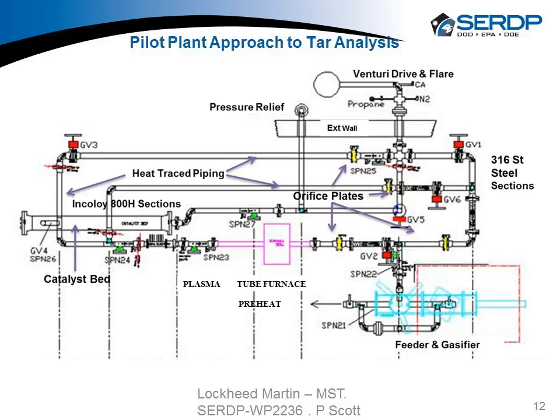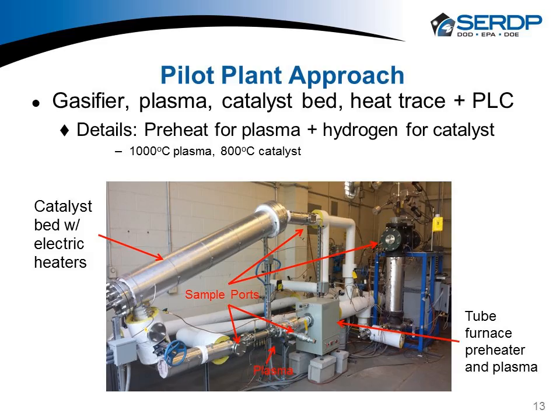So when we're going to run the process, we start, as I said, going right through the bypass. When we want to run the plasma, we would begin shutting this gate valve 1, opening the other gate valves, and then passing material through and out to the Venturi. If we want to run the plasma and the catalyst bed, we would open up gate valve 6. That gas blends with the gas that's coming out of the plasma, and ideally we would control the temperature of what's going into that catalyst bed and try to get to the activation temperatures with minimal electrical input. The catalyst bed is heated with electrical heat, and then there's a tube furnace. In the fine print for the plasma, you've got to be around 1100 to 1200 C for the plasma to really reform well, which is something we learned, and I had to add this after the initial planning was done, so that was a wake up there.